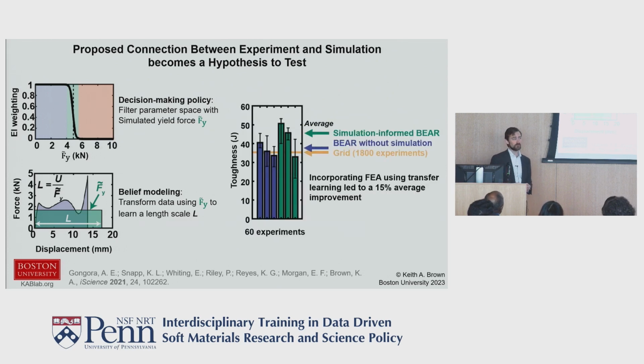And so when we do this, we find this is the result of a campaign where we ran 60 experiments. This is again on toughness or total energy absorbed. It turns out that it only took us 60 experiments with the naive bear without simulation to match our predictions, our grid. So in terms of acceleration against this grid-based searching, we usually say a factor of 30 based on this number. But more importantly, if we give the bear the simulation, we find that on average, we have a 15% improvement over the performance of the bear without simulation. And we find structures that were the very best we had ever found in this entire parameter space. So it's both faster and more effective.